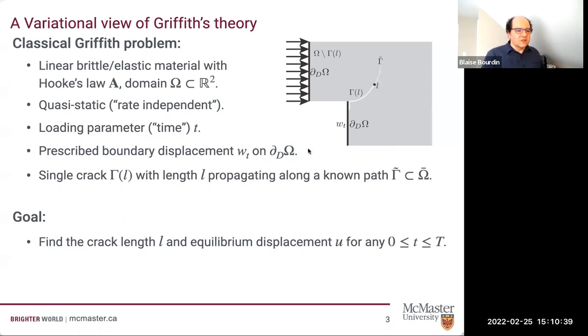Okay, my material is going to be subject to some boundary displacement on some part of the boundary. And I'm going to start by assuming that I have a single crack that propagates along a given path. So I'm going to call gamma tilde the known path of the crack. I'm going to assume that my crack only has one free end that moves along gamma tilde. So identifying the crack gamma of L would be equivalent to finding the curvilinear coordinate of its tip, or the crack length. So my ultimate goal at this point is, for any pseudo time t, finding the crack length L and the equilibrium displacement U.